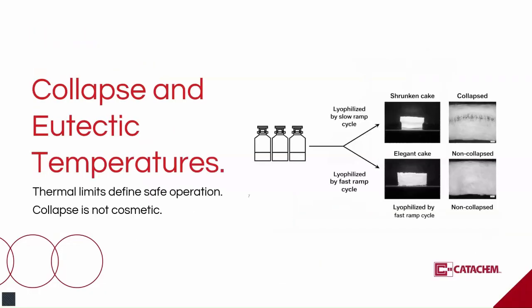Collapse temperature, TC, and eutectic temperature, TEUT. Awareness of these temperatures for a freeze-dried product are the key determinants in designing a successful freeze-dried procedure. The eutectic temperature is the melting point of a crystalline product as it freeze-dries. The collapse temperature for an amorphous product is where it starts to soften and lose structural integrity.